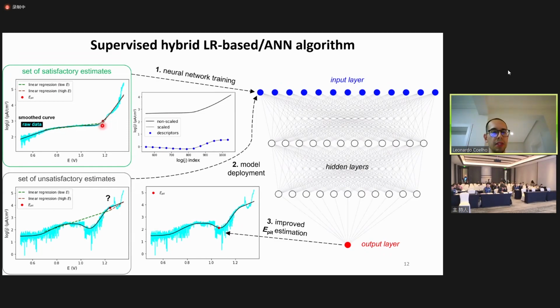So the first thing we did, we developed a simple linear regression, in fact, two of them. And this point is simply the sweet spot, the spot that maximizes the goodness of fit of these two regression lines. And this was able to solve 80% of our problem, but we would really like to achieve 100% in this case. We had about 1,000 curves, and we could have done it manually. So we could have collected these labels manually. Although I know, of course, all models have biases, I'm sure that if I had done that by hand, my bias would be worse over time after 1,000 curves.